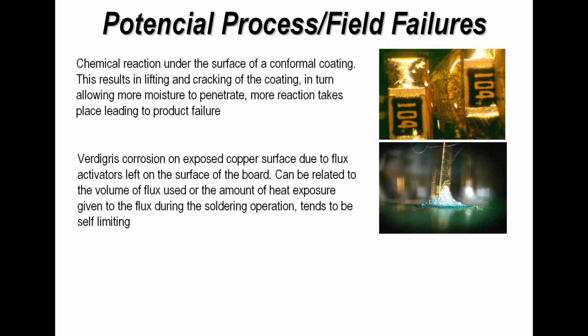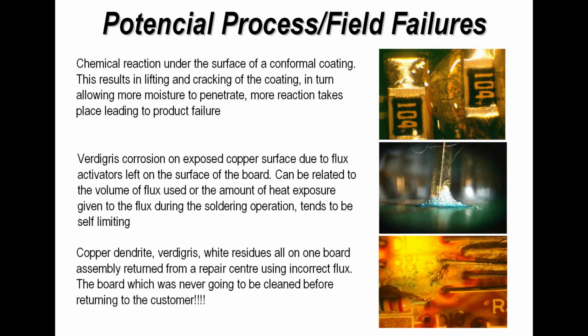This example photograph shows verdigris. This is a green corrosion deposit, normally seen on copper and copper materials, and normally is a reaction based on the flux residues left on the surface of the board. If you've got some reactive materials left on the surface of the board, verdigris can form. However, generally speaking, it looks worse than it actually is. And finally, the final photograph shows all three in one place at the same time.